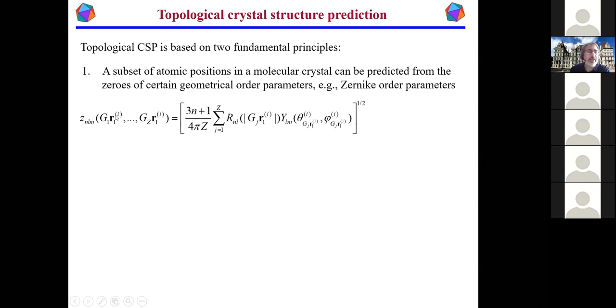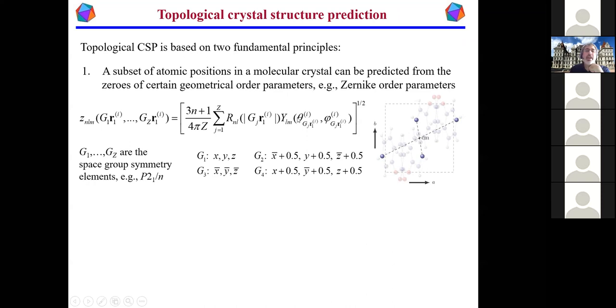You then apply the symmetry operations and you plug them into this form here, all right? So you have a radial polynomial, you have a spherical harmonic, and what you have to do in order to create this thing is to set up a set of bond vectors for how you get to each atom in the unit cell from a reference point, let's say the center of mass. Then you apply the symmetry operations to get your various locations. The bond vectors give you the length and the angles that you need, all right?